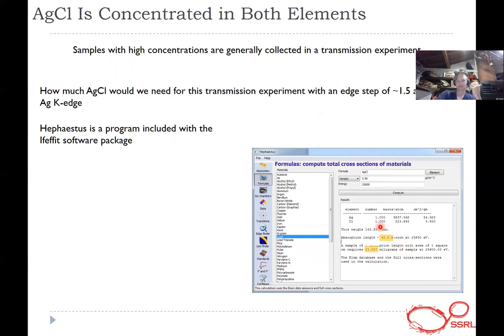You can see that it'll spit out an absorption length, and this number is important because you really need to ensure that the particle size of your sample is smaller than this if you can. What happens if this number is too big is you can get distorted spectra. The second number tells you how many milligrams of sample you will need in 1 square centimeter to get an absorption edge of 1.5. This is for a single absorption length, I'm sorry, and you can see the energy here at the silver K-edge.